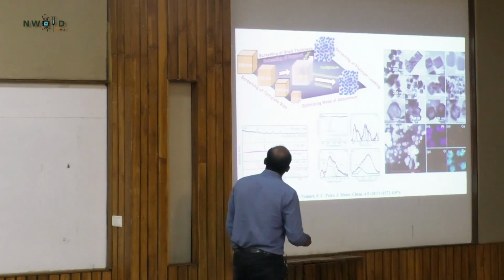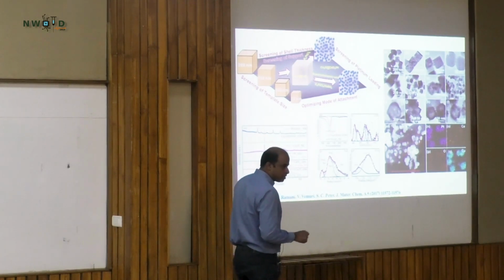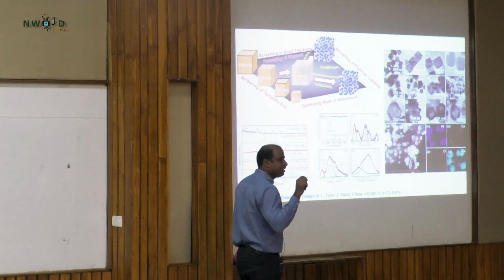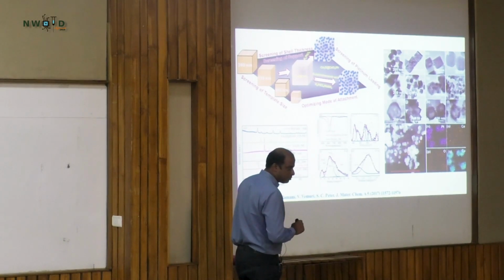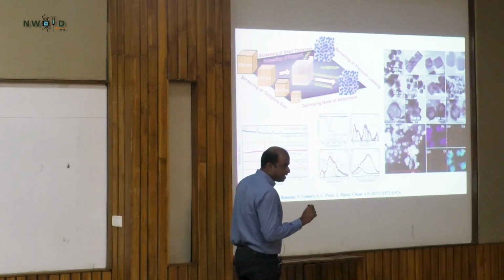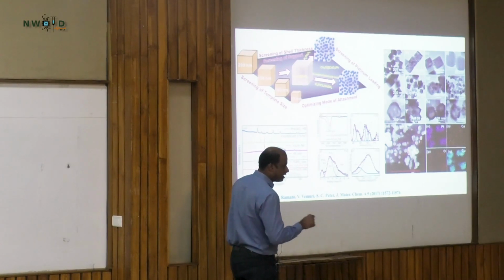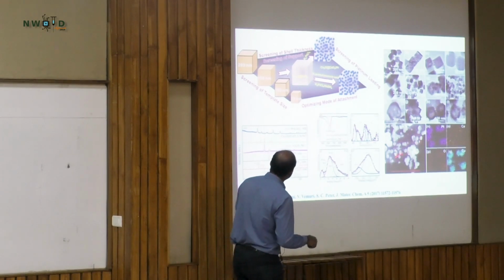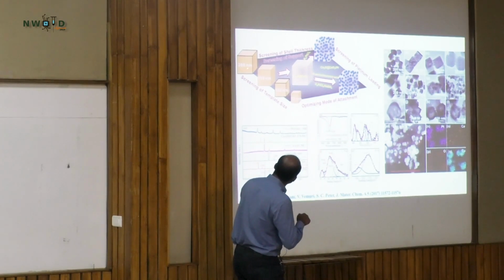Okay, so when it forms nanoboxes, platinum actually reduces at the surface of the nanoboxes. Platinum reduces the platinum metal at the corners and the edges mostly, and at the faces as well. And we have taken TEM images from each step, starting from this step to this step. And then you can see that there is a change of the shape.